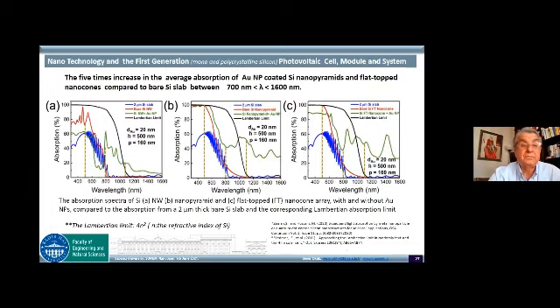Some recent results use gold metal nanoparticles, and they really plotted three different conditions for three different structures. But as you can see, when you go to the Lambertian limit, which is 4n², within that, in the infrared region, you can even beat the Lambertian limit. You can see the absorption of bare silicon, absorption of bare nano textures, and what happens when you add the metallic nanoparticles on those nano surface textures. It is an important progress, an important area, and believe me, significant research and technological development work is going into this area.